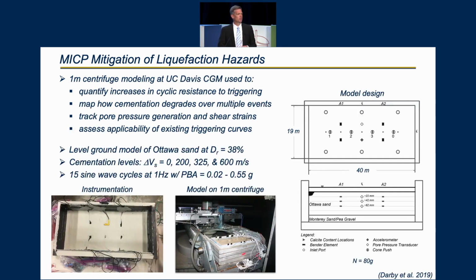And so in this case, the 1 meter centrifuge at UC Davis was used to quantify the increase in cyclic resistance to triggering, to map how cementation degrades over multiple earthquake shaking events, to track pore pressures and shear strains, and to assess the applicability of existing triggering curves. And so just a simple cross-section of the model on the right-hand side, you can see it's a relatively simple level ground condition. Under 80 G, this is simulating about a 10-meter deep, loose liquefiable deposit.